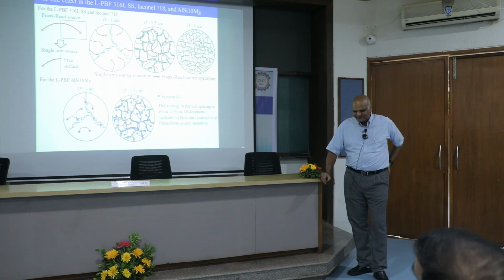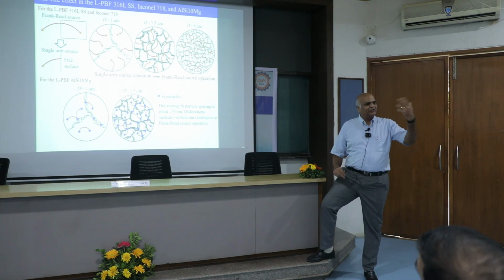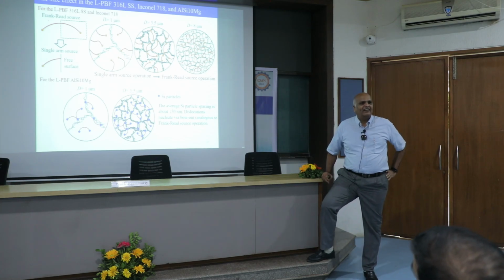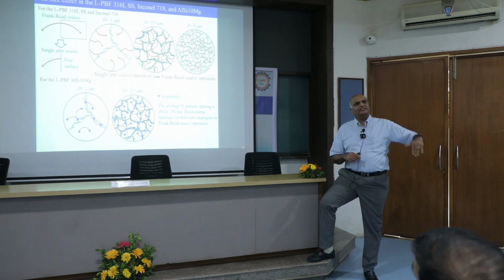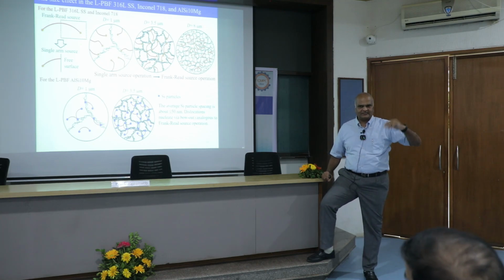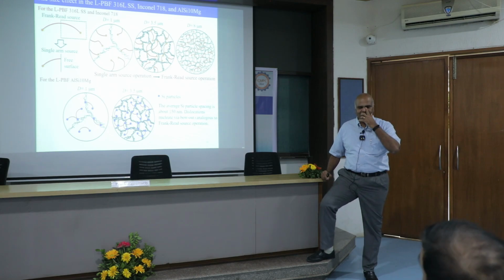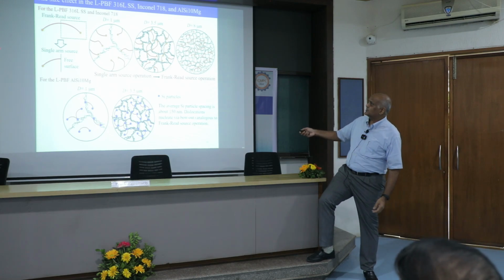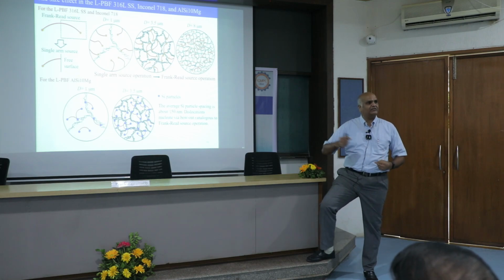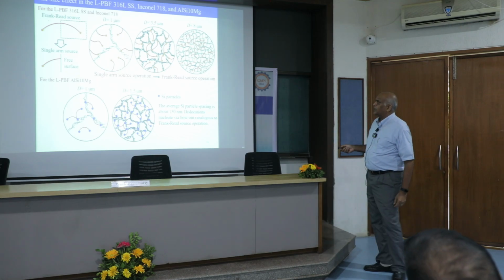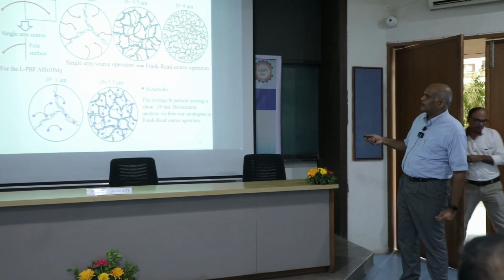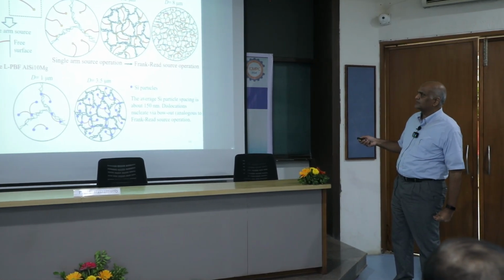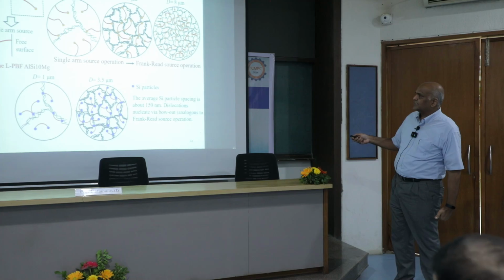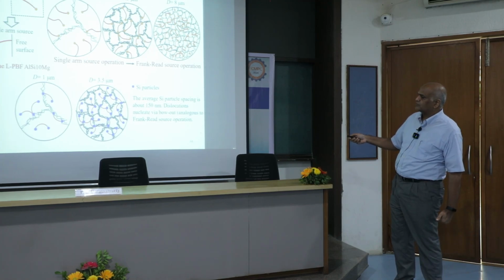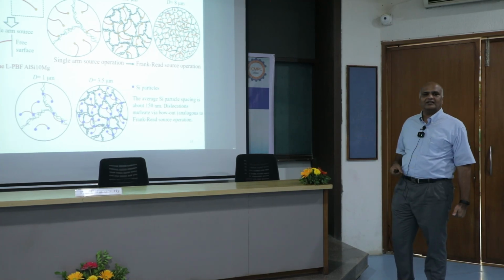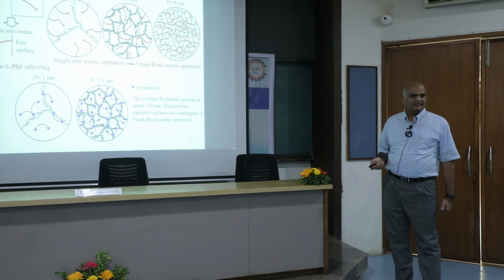What happens is, if you take a well-annealed gold piece and hit it with a hammer, the dislocation density goes up inside the material. That's what causes work hardening and strengthening. So the mechanism is that these kinds of sources keep punching out dislocations. Now when you have very small diameter specimens, essentially micropillars, in the free surfaces you have what is called a single-arm source, and they operate and cause this strengthening.